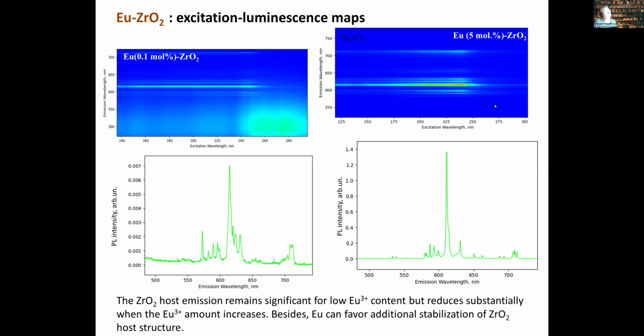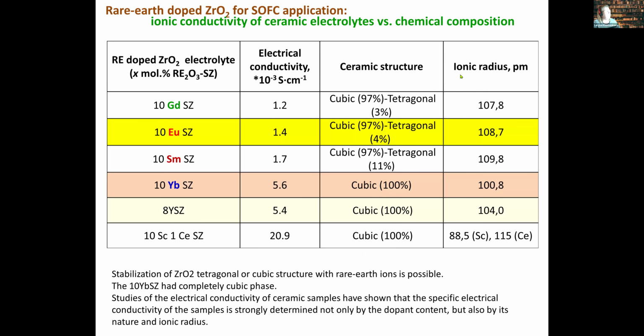It can disappear due to two things. First of all, it may already transfer all the excitation to the rare earth ions. Otherwise, it can also be a possibility that the europium dopant also stimulates transformation from monoclinic phase to tetragonal or cubic phase. And this point needs some confirmation. Raman scattering spectra confirm this idea, but we need more structural characterization. And just one point, that if we use europium dopant, it really stabilizes, as we asked our colleagues, and they told us that it definitely stabilizes cubic and tetragonal structure with a high amount.